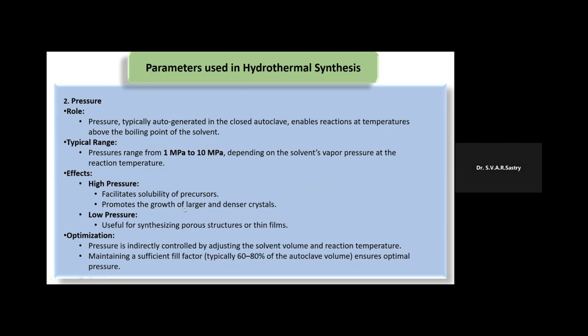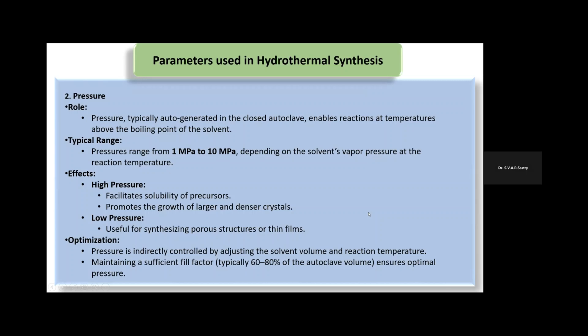Regarding the effects of pressure, high pressure facilitates the solubility of the precursors easily. It also promotes the growth of larger and denser crystals. Whereas lower pressure is useful for synthesizing porous structures or thin films. Then optimization is required again. So pressure is indirectly controlled by adjusting the solvent volume and the reaction temperature, maintaining a sufficient fill factor, typically between 60 to 80% of autoclave volume, which ensures optimal pressure.